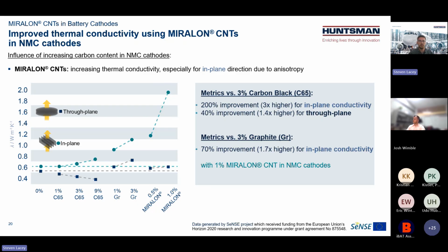so 1D and 2D character, we have a significant improvement in the in-plane conductivity versus carbon black and graphite. So 200% improvement or 3 times higher versus carbon black with a third of the material. But also from the through-plane perspective, we have about 1.4 times higher conductivity in this direction. And when you compare directly to graphite, which is a very well-known thermal conductor, we also see improvements, especially in the in-plane conductivity. So this also shows that this conductive additive plays more roles than just electrical conductivity.